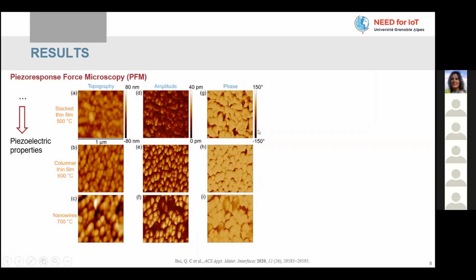On the phase, what we see is the polarity. For example, here the bright zone is the zinc polarity, and the dark zone is the oxygen polarity. We see that there are both polarities on thin film, but when it changes to the nanowire, it has a more uniform zinc polarity. For the nanowire, because there are some gaps between the nanowires, it's not a dense layer, so this signal is noise, because we fill those gaps with PMMA, one kind of polymer, to keep the scanning tip of the piezo force microscope in contact with the sample.